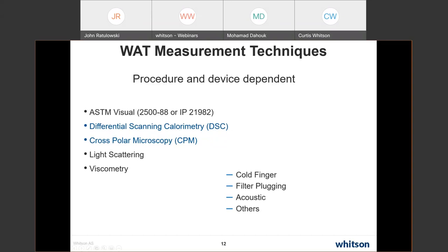Cross-polar microscopy, here we have two filters, and it's a visual technique. We have two filters that cross-polarize the light, and what happens is if the light passes through the crystalline wax, it's rotated so that the other filter on the back side does not filter out the light. So because of the rotation of the light, you'll see a white spot in CPM where there's crystalline wax. And again, we come back to, if it's not crystalline, you won't see it. So if you have a microcrystalline wax coming out, it's going to be very difficult on a CPM to actually see it when it comes out.